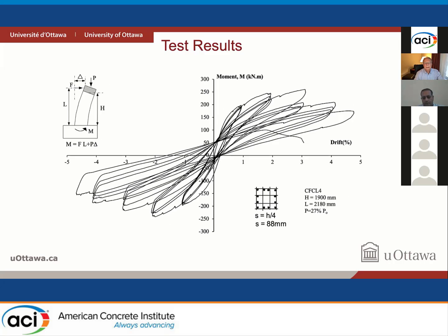If we look at the next hysteretic response, which is under 12-bar arrangements, we had similar behavior, and our conclusion from this reverse cyclic loading was that we were able to introduce some level of ductility and reasonable deformability, going up to 2% drift, by gradually crushing confined concrete rather than reaching the limits of the material.